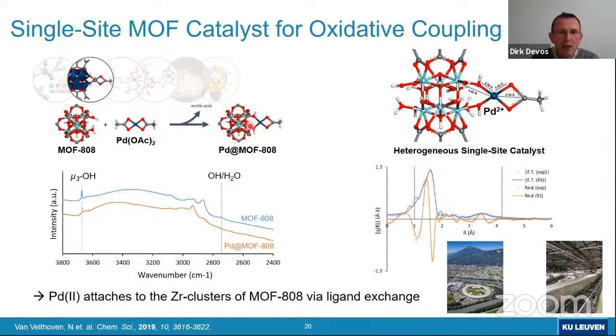In fact, if you think about it, the cluster just takes over the role of a ligand with a -1 negative charge, just like the other remaining acetate on the palladium, meaning that the palladium is really monoatomically dispersed all over the clusters of this MOF material. And actually, Niels took all the effort to document that process also with vibrational spectroscopy. So there are the mu hydroxyls on the MOF-808, but especially here you can also see these other hydroxyl groups, which are shown here. You can also see them in the infrared spectrum. And then if the hydroxyl-containing MOF-808 reacts with the palladium acetate, you see the disappearance of these hydroxyl groups. And that's proof for an anchoring of the palladium on these clusters.